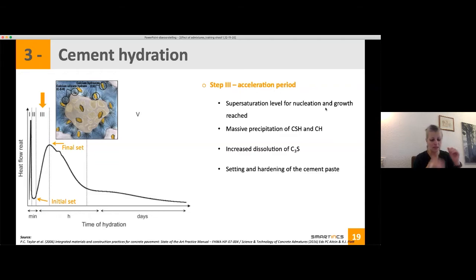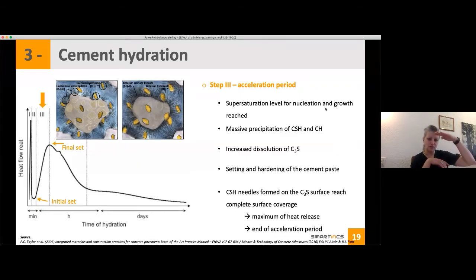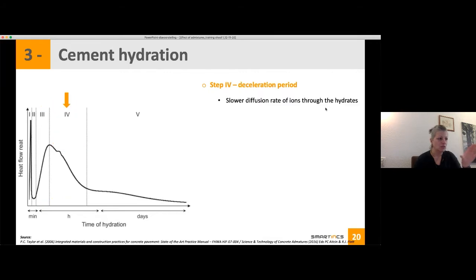And then you can see that you have the top of this curve. And it means that the CSH that precipitates in a needle-like form will cover the surface of your cement particle, and then it will decrease again the speed of reaction. So it's what you see in part 4. So part 4 is a deceleration period. And that means because you have a layer of hydrates, you have a slower diffusion of the ions through the layer of hydrates.